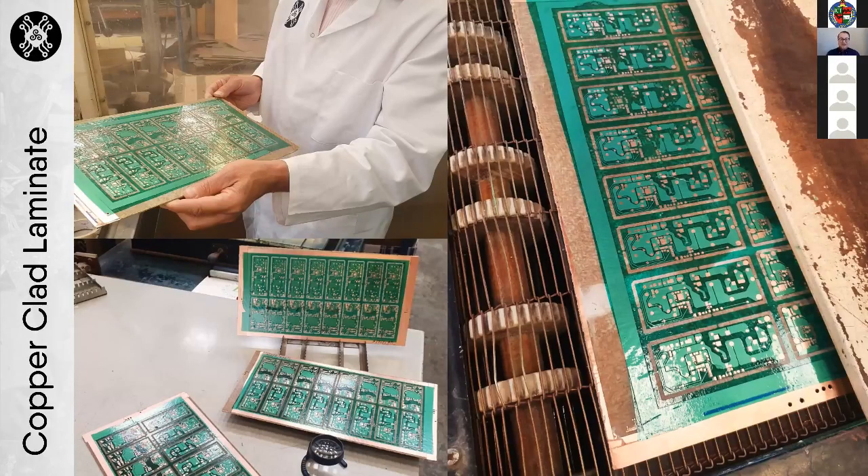We've also been developing a woven variation of solid board, as opposed to the unidirectional material shown until now. This is more in line with the formulation of a material used in FR4. Substituting unidirectional fibres with a weave will help reduce costs and achieve the XY mechanical performances required within the industry. We've now successfully produced PCBs using industry-standard subtractive fabrication processes, and used some of these boards to test recycling of the woven variation — which has also gone very well.